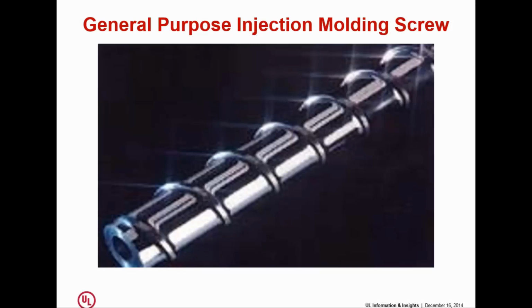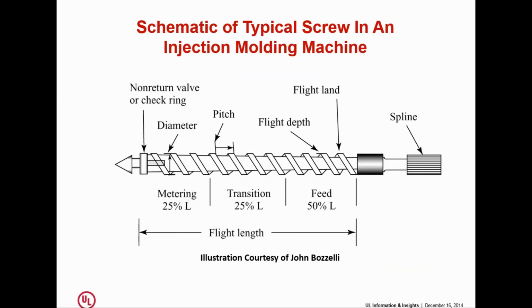Now, the geometry of these screws is pretty predictable. You have a particular amount of flights that are devoted to what's called the feed section. You have a particular amount of flights devoted to what's called the transition section. This is where the melting process actually is supposed to start. And then you have the metering section. You'll notice that the depth of the flight gets shallower, gets smaller as we move from back to front. The ratio of these flight depths is what we call the compression ratio. And very often what people will counsel you to do is use a compression ratio that is optimal for the material you're processing. Sounds good.